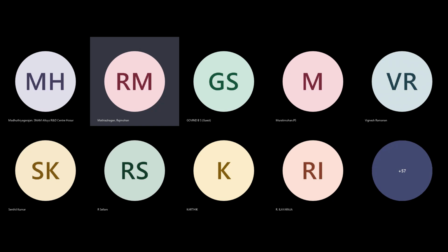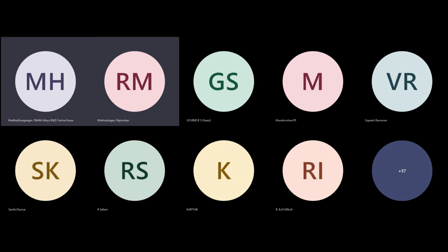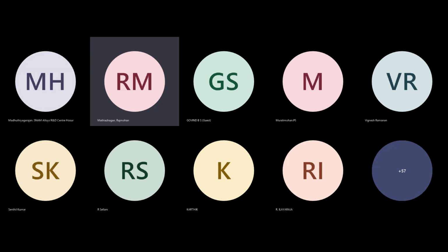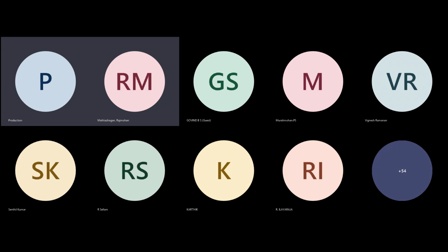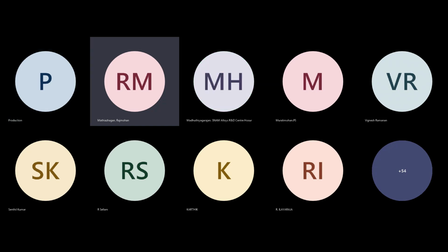But in general, on boric acid versus boron oxide, we always recommend boron oxide mixes, because boric acid is hygroscopic in nature. Boric acid is H3BO3 and boron oxide is B2O3. In the past, people mixed the boric acid on the shop floor and put it for preheating at around 80-90 or 100 degrees Celsius. But there is still chemical moisture involved, which will not escape. This chemical moisture will escape only at 400 or 500 degrees Celsius, that is, when the lining is inside the furnace, and it will create porosity on the hot face. In the case of boron oxide, all this chemical moisture has already been eliminated, so your hot face formation is much better compared to boric acid linings.